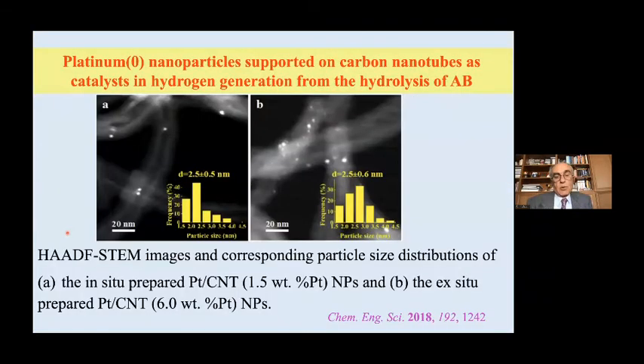And one can see that platinum nanoparticles of the same size can be formed either by in situ or ex situ preparation technique. That means in situ during the hydrolysis of ammonia borane. That means the reducing agent is ammonia borane and slow reduction, while in the ex situ, sodium borohydride has been used somewhere else to prepare the nanoparticles and then bring the nanoparticles.